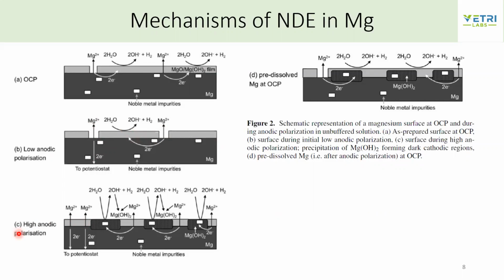When there is high anodic polarization, that is, they try to increase the current to a much higher level, they have a completely different oxide film here, which is completely enriched with noble metals, and that increases the hydrogen evolution kinetics. So when they bring it back to OCP, these films still remain, but then due to the potential, they again have a magnesium hydroxide film, but this film is much more porous and different compared to the dark film. Because of these changes in the surface film characteristics as a function of pH, they state that the NDE occurs in magnesium.